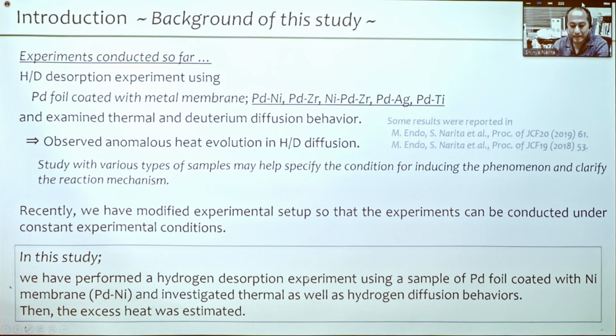Okay, so considering these conditions, we have conducted the hydrogen and deuterium desorption experiment using the palladium foil coated with the metal membrane, such as the palladium nickel and palladium zirconium, and something like these samples. And we examined the thermal and deuterium diffusion behaviors. Then we observed anomalous heat evolution in the hydrogen and deuterium diffusion process. And we think the study with the various types of sample may help specify the condition for inducing the phenomena and clarify the reaction mechanisms. So some of our results are also shown in these references.